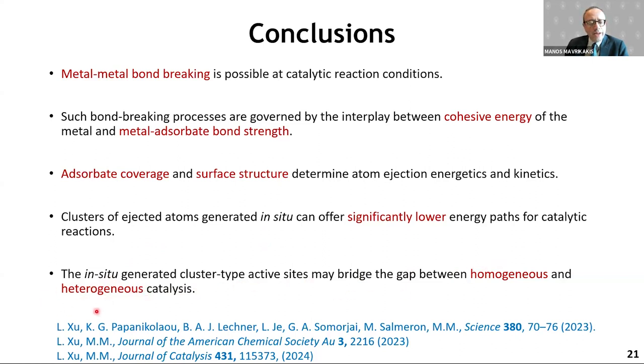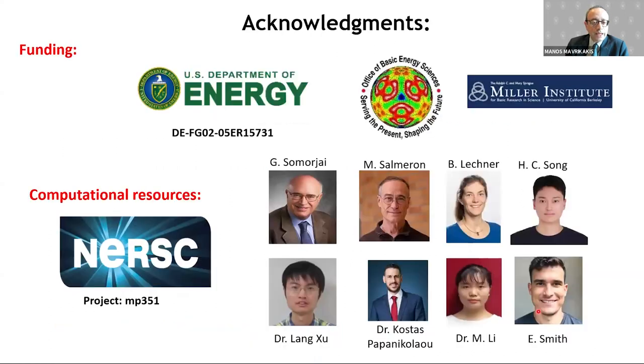The smaller the number of metal atoms implicated in a heterogeneous catalysis active site, the closer you get to homogeneous catalysis active sites, because in homogeneous catalysis, one or two metal atoms are typically included in the active site, the rest is ligand. So I think this is an interesting connection that may be developed. So essentially, you generate in situ pretty much your homogeneous catalytic active site in the context of heterogeneous catalysis.